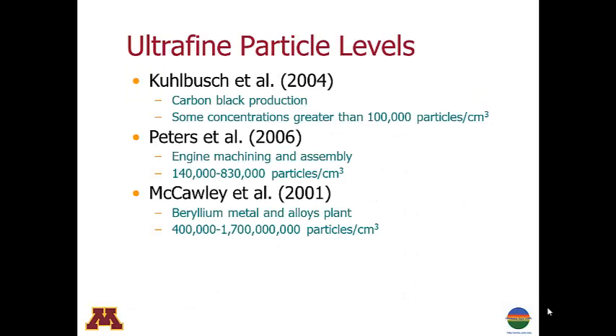How do the particle number concentrations observed in our tests compare with real-world particle levels seen in other research studies? In 2004, Kuhlbusch et al. looked at carbon black production and found concentrations greater than 100,000 particles per cubic centimeter, which is higher than any of the levels that we were able to observe.